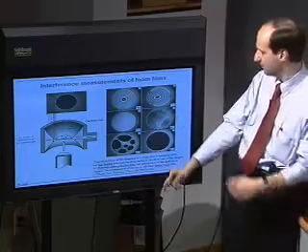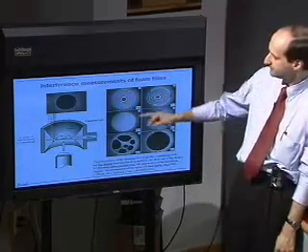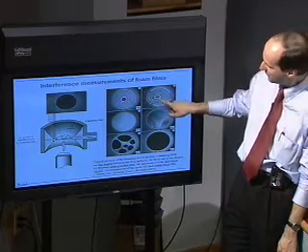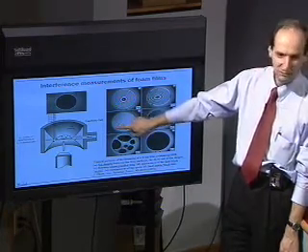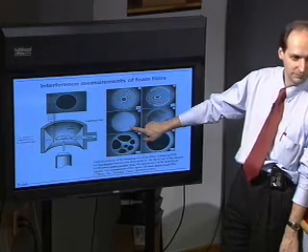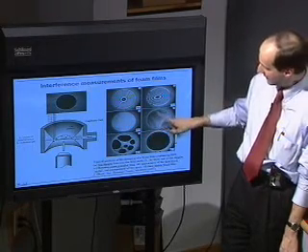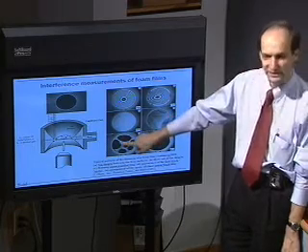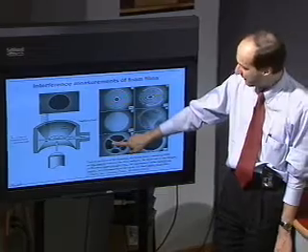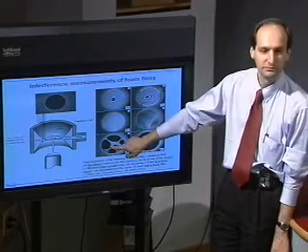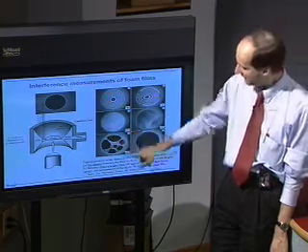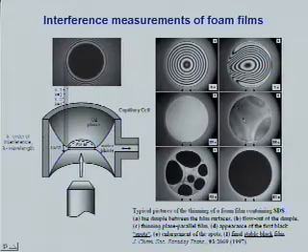This is actually from a paper where I'm a collaborator. There is a thicker film in the middle, which falls out. You have a plane parallel thick film, which is bright. Then this film thins a little bit further, and suddenly you see those spots. You see a jump-wise transition from a thick film to a thin film. So the film is either thick or thin, and then the thin film spreads out and occupies the whole area.